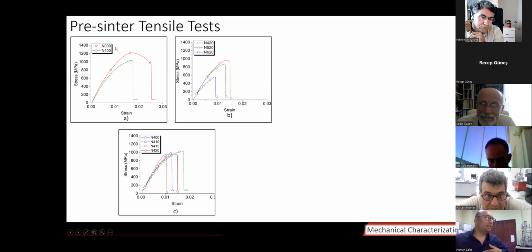Okay, what we see is that the N00, this is pre-sinter state. In the pre-sinter state, I want to tell you that all the sheaths are strain hardened, and they are not subjected to boriding treatment, and the cores in the wires have iron and B4C particles which are very small. So we can expect that they are not going to influence the tensile behavior of the wires dramatically. So presence of a core has resulted in reduction in the tensile strength and also reduction in the strain of the wires.